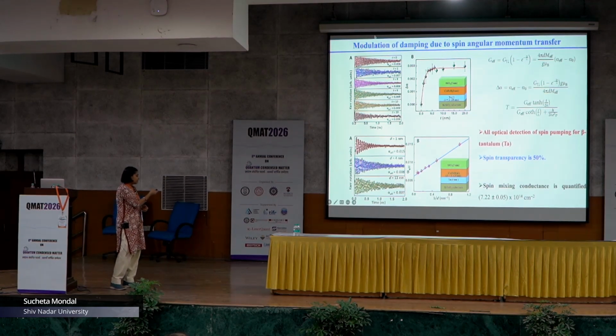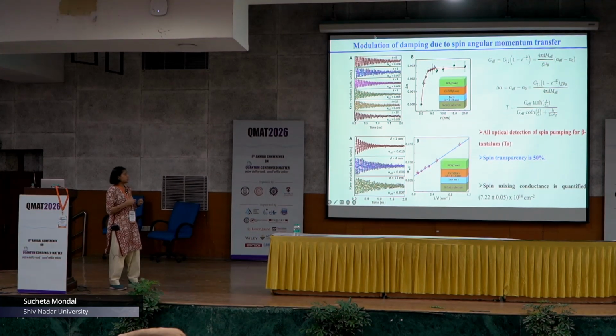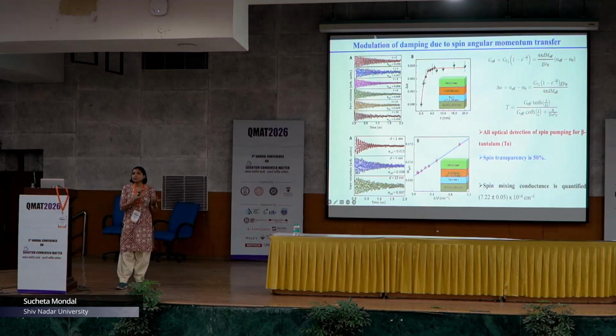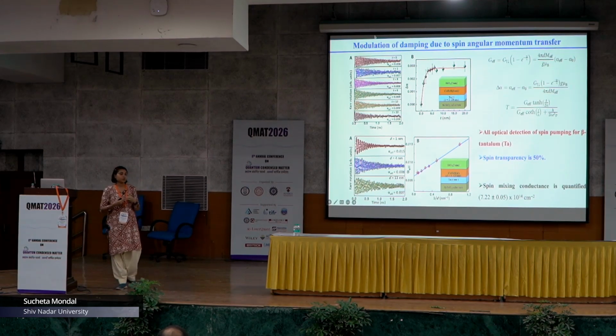So the role of the interface is very important in this case, because there is an interfacial transparency term, called the effective spin mixing conductance, which is a measure of how good the interface quality is between the tantalum and cobalt-gadolinium. For us, the reported spin transparency is about 50%, which means the beta-tantalum and cobalt-gadolinium interface which we have formed allows 50% of the total spin current to be transferred. If you can improve these interfacial parameters, then you will apply less energy to the system and simply get more output.